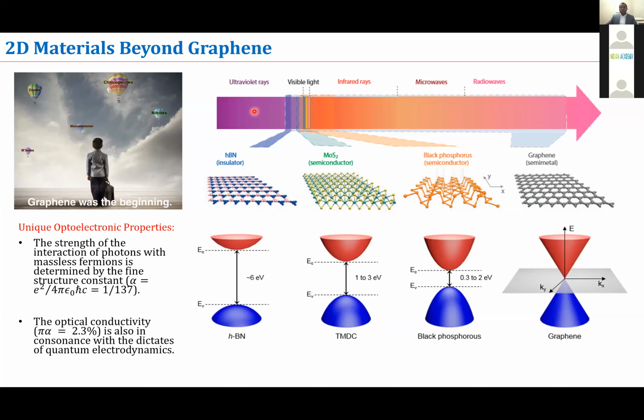So if we look at the energy spectrum, then graphene, because it has zero band gap, can cover almost a broad spectrum of energy, starting from visible light to infrared to microwaves or radio waves. Then you have boron nitride, it has 6 electron volt that corresponds to the UV part of the spectrum, because ultraviolet light has a high energy. And then these are semiconductor transition metal dichalcogenides like molybdenum disulfide or tungsten disulfide. They correspond to the visible part of the spectrum because their band gap varies from 1 to 3 electron volts.